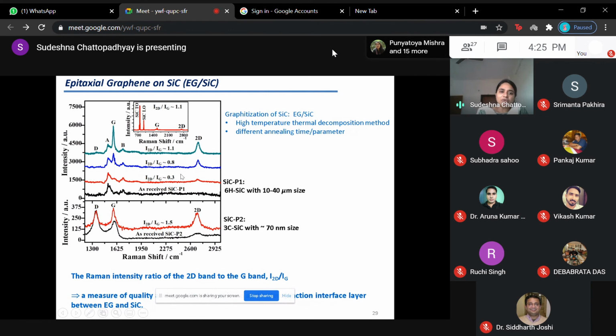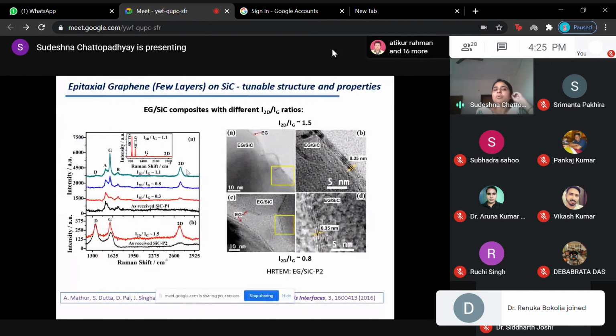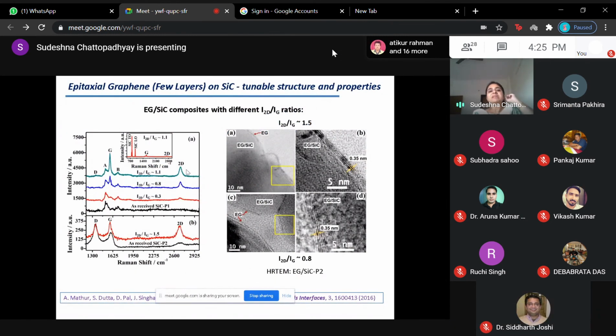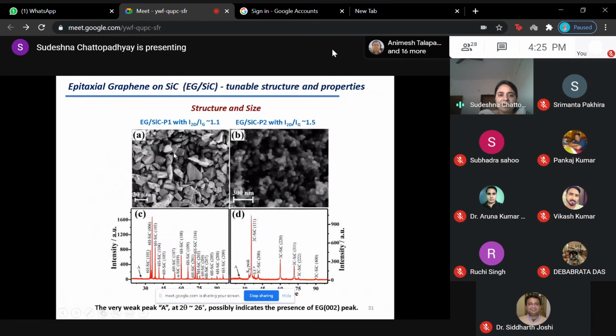You can see I2D by IG of 0.3, 0.8, 1.1, so it is getting better here, and that way we have named the samples by I2D by IG. That means it is the parameter. So we see how the quality of the graphene is getting better, and in that way how the photocatalytic effect can be better, worse, or whatever it is. Then of course Raman, as I have told, you can see qualitatively, and in this case we have chosen particles, 70 nanometer, 10-40 micron, like that. So here you can see the particles. This kind of particles we have taken.